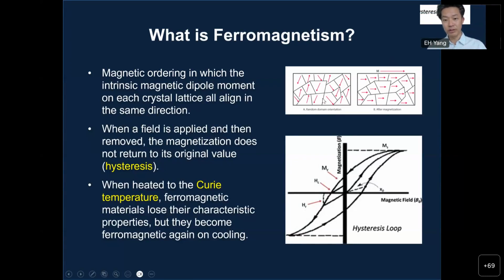So, on the left, there is a random domain orientation, and after magnetization, you have this aligned magnetic dipole moment here. Now, this is after the field is applied, and then you remove it. What happens is the magnetization does not return right away. That's called hysteresis. From this hysteresis, you can get the magnetic coercivity, and you see how much magnetic field this material will generate, and so on and so forth.